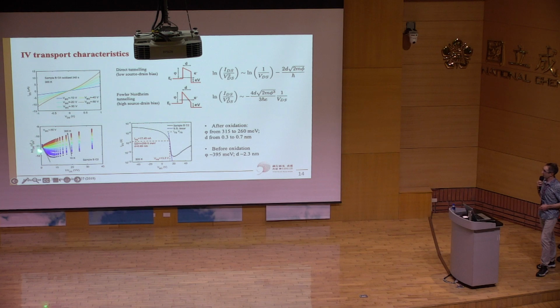So we can use this data at the lowest temperature, take the linear part of this curve and really estimate what our width and height of the barrier is. We find that after oxidation, barrier heights are around 300 and widths from 0.3 to 0.7. Before oxidation, barrier heights are reasonably similar, same order, but the barrier widths are much bigger. So it's telling us that our oxidation process is giving us more control over the barrier width rather than the height.